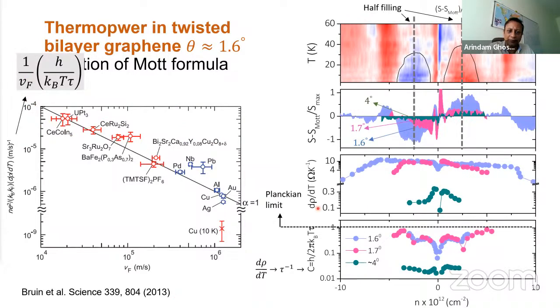What we see is, I just want to say that there is a limit called a Planckian limit in the half filling, in the strong correlation limit, where the electron-electron interaction poses a serious question about how well-defined your quasi-particles are, and the dissipation reaches the maximum because your quasi-particles are no longer very well-defined. So we find that this probably is a system which has a very strong similarity to what you call a strange metal. And we essentially found that that region is near the half filling where the electron-electron interaction is very strong.